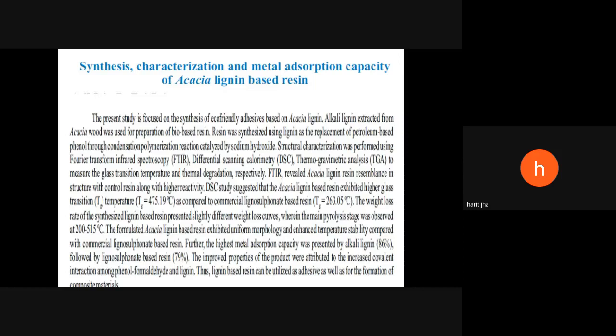The structural characterization was performed using FTIR, DSC, differential scanning calorimetry, then thermogravimetric analysis to measure the glass transition temperature and thermal degradation respectively. The FTIR revealed that acacia lignin resin resembles control resin along with higher reactivity. DSC study suggested that acacia lignin based resin exhibited higher glass transition temperature as compared to commercial lignosulfonate based resin. The weight loss rate of the synthesized lignin based resin presented a slightly different weight loss curve, where the main pyrolysis stage was observed between 200 to 515 degrees centigrade. The formulated acacia lignin based resin exhibited uniform morphology and enhanced temperature stability compared with commercial lignosulfonate based resin.